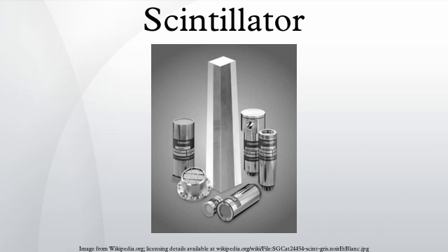Aside from the aromatic plastics, the most common base is polymethyl methacrylate, which carries two advantages over many other bases: high ultraviolet and visible light transparency, and mechanical properties and higher durability with respect to brittleness. The lack of fluorescence associated with PMMA is often compensated through the addition of an aromatic co-solvent, usually naphthalene. A plastic scintillator based on PMMA in this way boasts transparency to its own radiation, helping to ensure uniform collection of light. Other common bases include polyvinyltoluene, polymethyl, 2,4-dimethyl, 2,4,5-trimethylstyrenes, polyvinyl diphenyl, polyvinyl naphthalene, polyvinyl tetrahydronaphthalene, and copolymers of these and other bases.